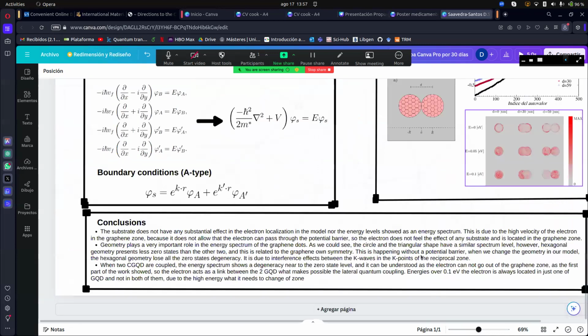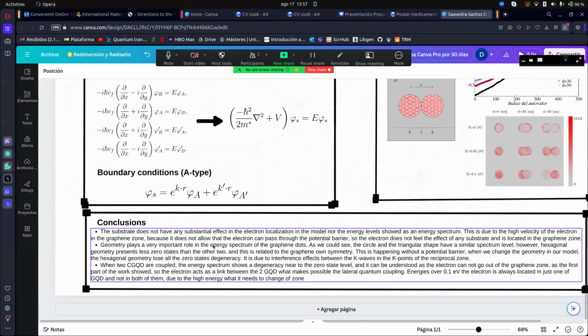The conclusion that this work has is that the substrate doesn't have any substantial effect on the electron localization in the model, nor on the energy levels shown in the energy spectrum. This is due to the high velocity of the electron in the graphene, because it doesn't allow the electron to pass through the potential barrier. So the electron doesn't feel the effect of any substrate and is located just in the graphene.